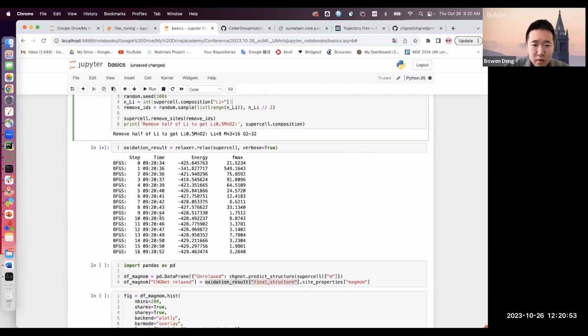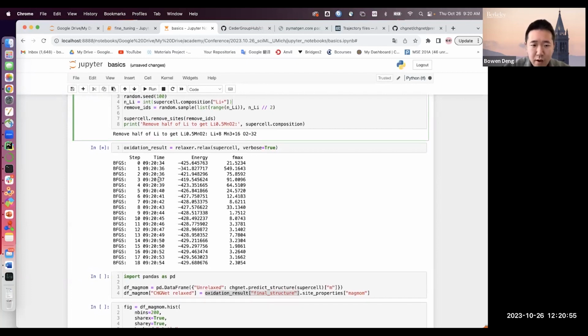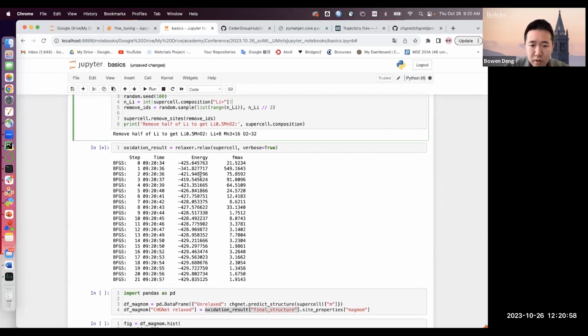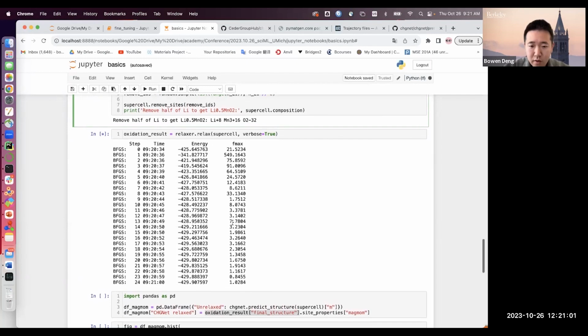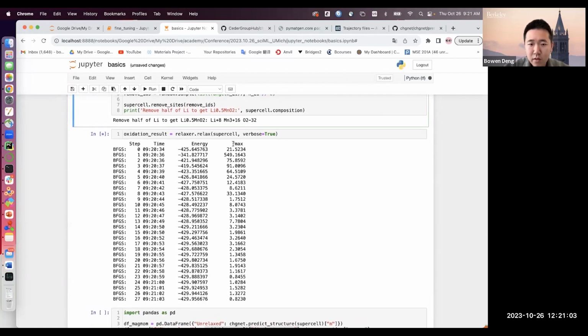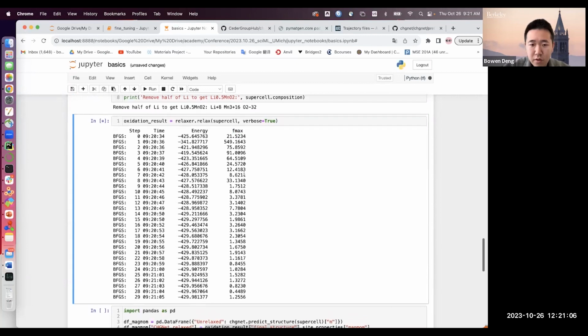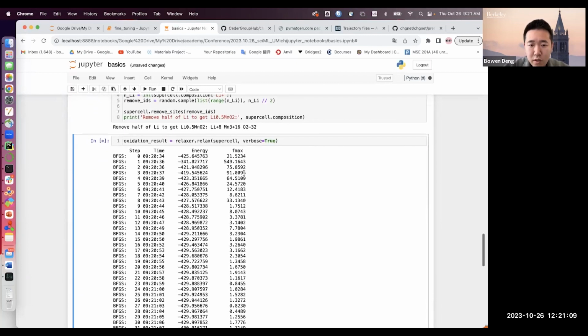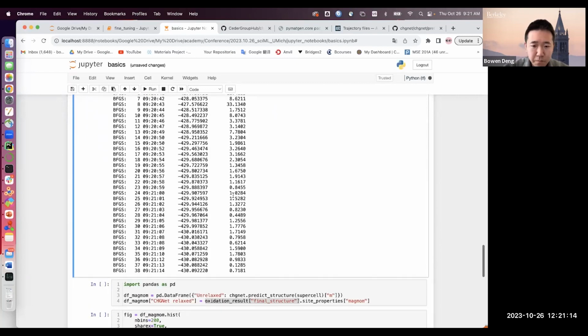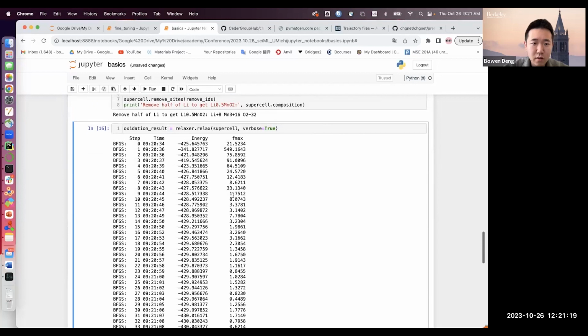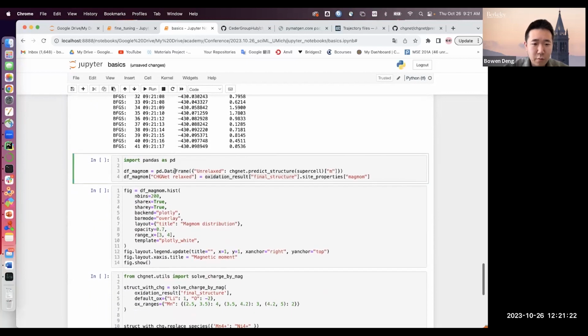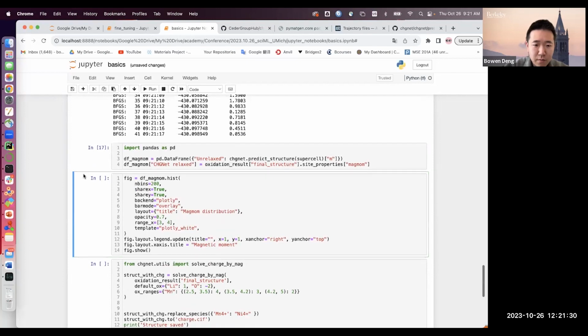And here you can see, it essentially tells you the time taken at each step, the total energy of the system, and also the maximum force that's experienced by these atoms. And the fmax here is actually an effective force that combines both the forces on each atom and also the stress on the cell. Yeah, it's completed.